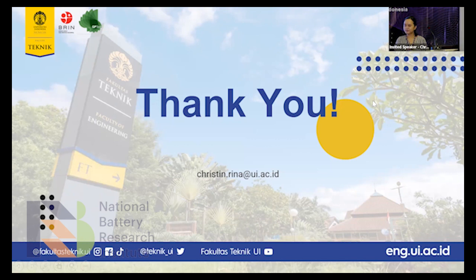It's quite interesting because I have similar research to yours. My question is, what kind of polyvinyl alcohol do you use? As you know, polyvinyl alcohol has different types. It depends on the degree of polymerization and degree of hydrolysis. If you are using partially hydrolyzed PVA or fully hydrolyzed PVA, it will have different results. So what kind of polyvinyl alcohol did you use in your research? Thank you. In this experiment, we use partially hydrolyzed PVA with a molecular weight of 89,000.